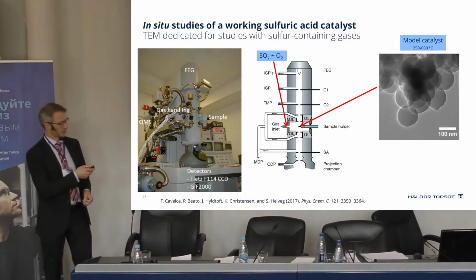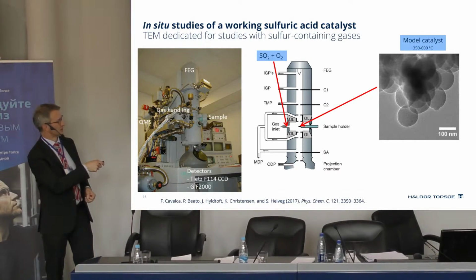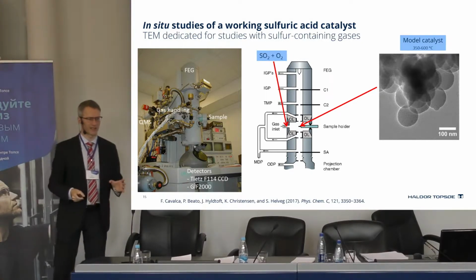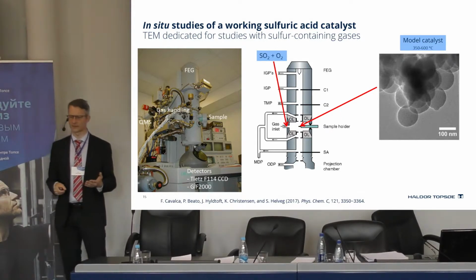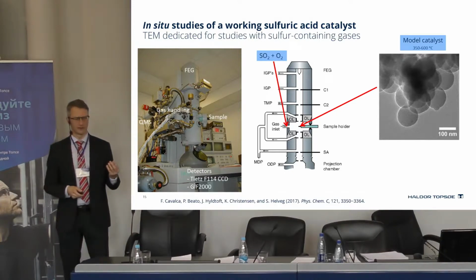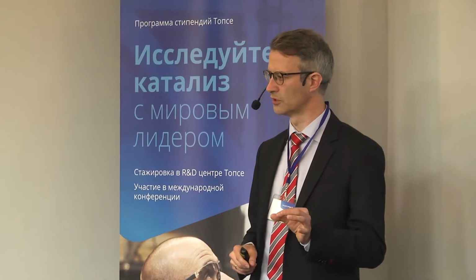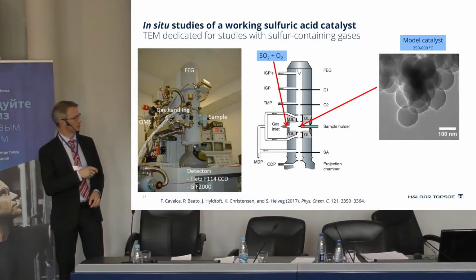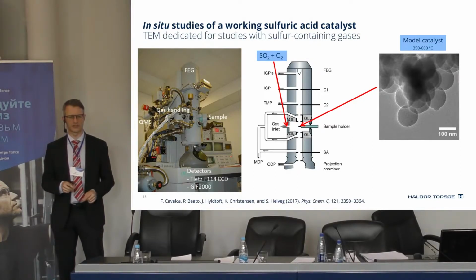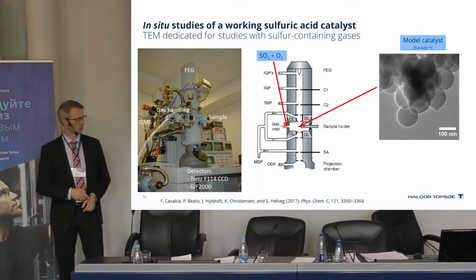So in this case, we feed some SO2 and oxygen around the sample here, and you can see that we have put in a catalyst. And this is a model catalyst, and the reason for using a model catalyst is because we want to see the basic phenomena taking place, and that's easier if we have a model catalyst. Here the silica is round 100 nanometer spheres, so-called Stoeber spheres, that we've used to make this catalyst. So they are easy to identify. The way to maintain this gas pressure is to use a differentially pumped vacuum system in the microscope, and still then we can maintain the high resolution of the microscope.